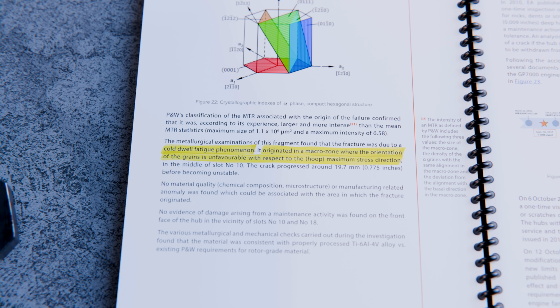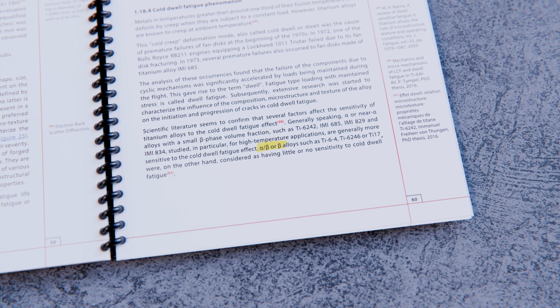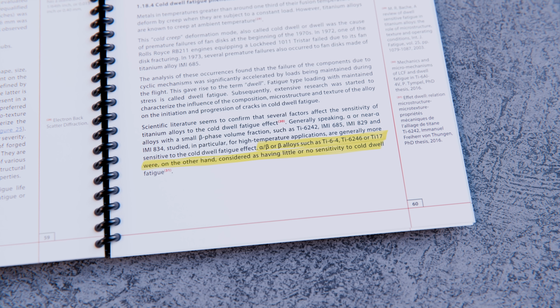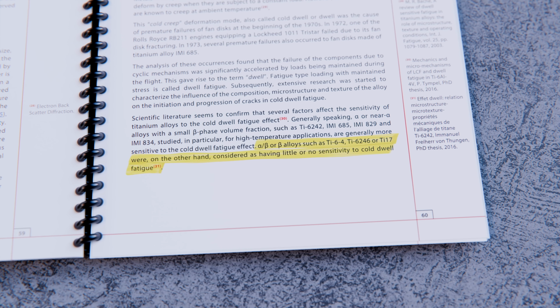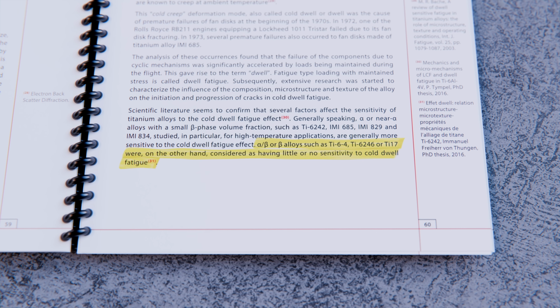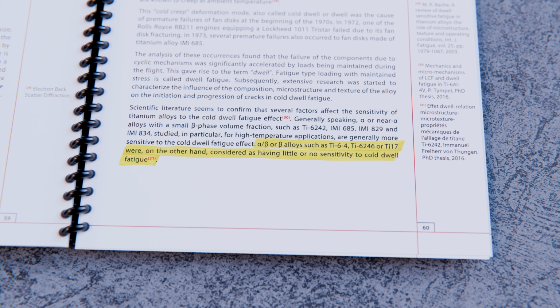Cold dwell fatigue failures had happened before, but it was thought to mainly affect alpha alloys. This was the first time a component made of Ti-64, the workhorse titanium alloy of the aerospace industry, had failed in service due to cold dwell fatigue.